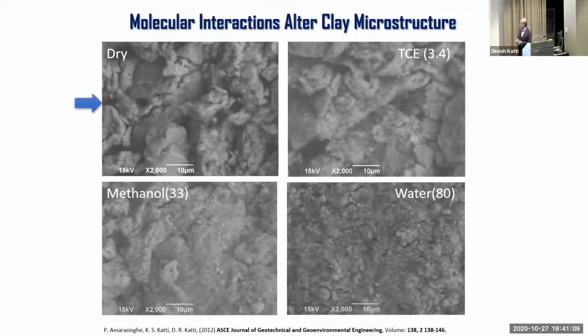So if we look at the left-hand top image, what you are seeing there are relatively large particle sizes, and then you're seeing spaces between the particles or voids between the particles. Okay, those are clearly visible at this scale. Now, let me ask you to take a look at the image on the right-hand side bottom of your screen. And this is where the water has seeped through the clay. And what you see here is that the particles have broken down into smaller and smaller particles, and we really don't see any visible spaces or voids at this scale.